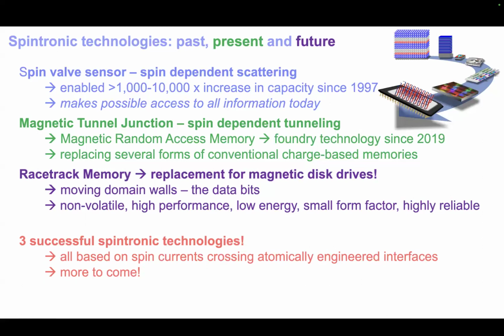Thank you. So an obvious follow-up question there is, are there materials or structures known where the successive domain walls have opposite chirality? No, that's not true. They always have the same chirality, or random chiralities if you don't have, let's say, the Dzyaloshinskii-Moriya interaction. So it's just the DMI that biases it to select a single chirality, and if you don't have it, you get random. Correct. Okay.